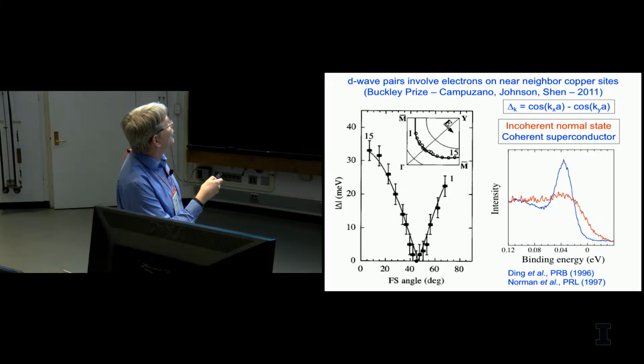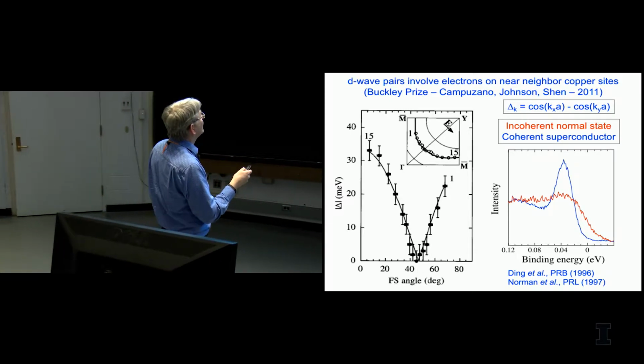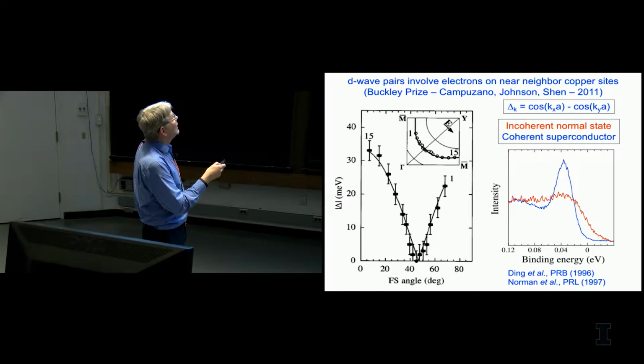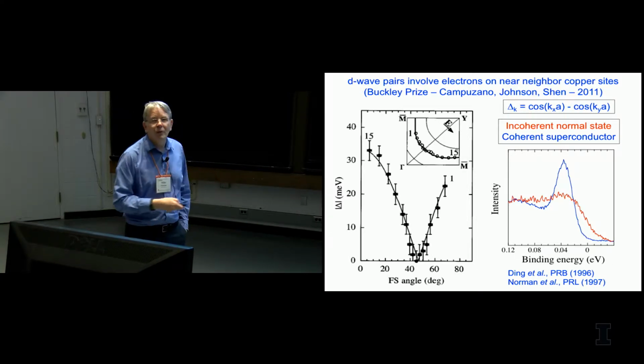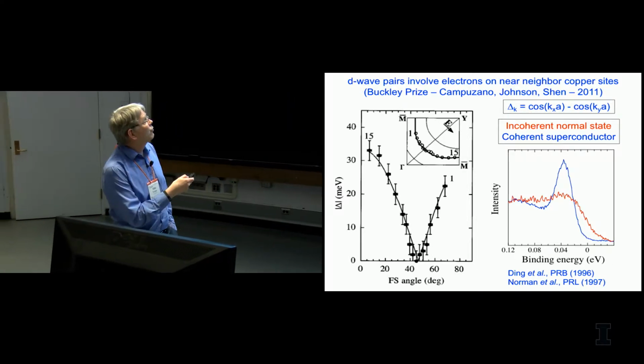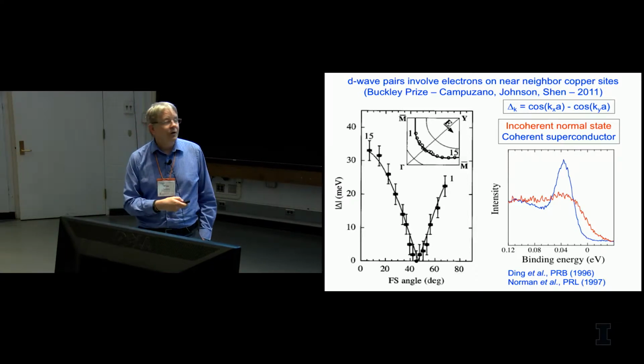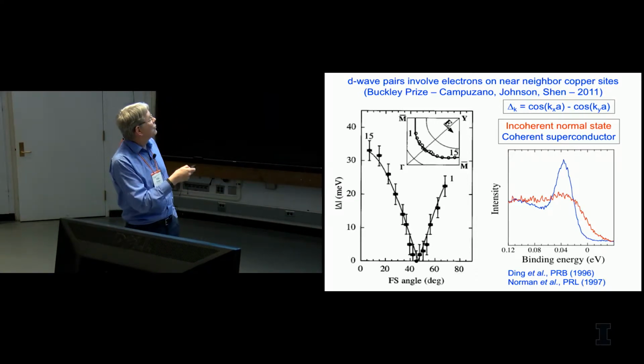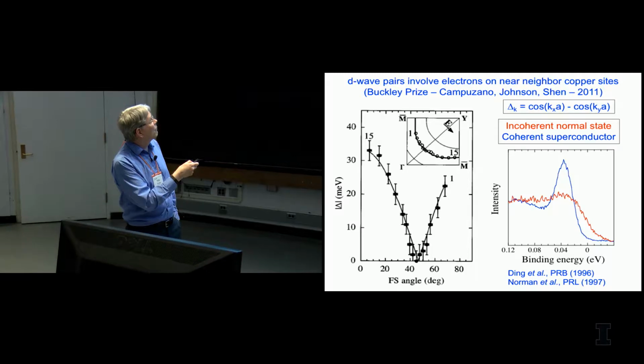The reason why we know this is that the angular dependence of the gap can be measured by, in this case, angle resolved photoemission, and it fits this formula cosine x minus cosine y, which is a Fourier transform of electrons sitting on near-neighbor copper sites. So that's important fact number one.